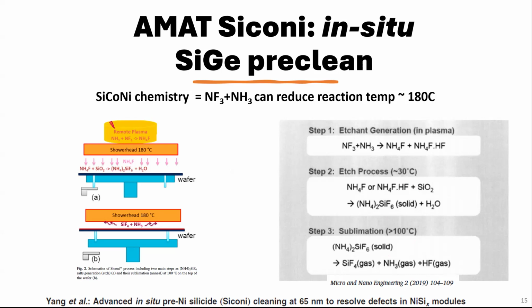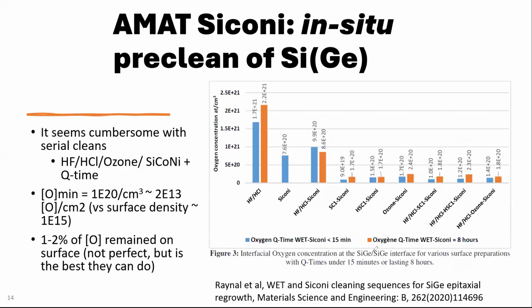Okay. But is that enough? No, that's not enough. You look at the actual process. The actual process, this IMEC work, I think did a pretty good job. They did a lot of experiments to find a solution to improve, to get rid of oxygen as much as you can. So what's the POR process? Well, POR process is here, HF and HCl. These two tanks, you went through the machine, the wet bench. You take the wafer out and a conveyor belt will run, and put it into the high K machine. But at the moment you take it out from the wet bench, you start to oxidize. The oxides come back in 30 seconds.